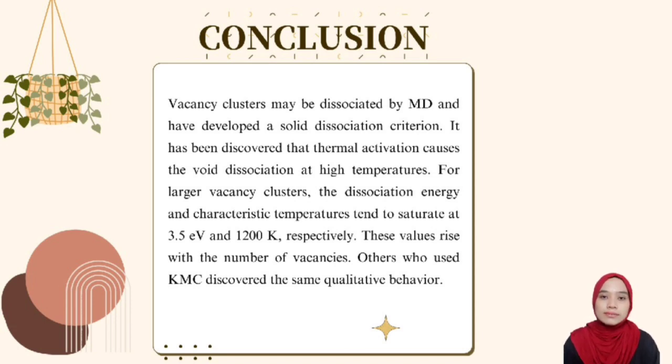As the single vacancy migration barrier is somewhat underestimated by the utilized EAM potential compared to the DFT value used by KMC, our estimates for dissociation energies and characteristic temperature are a bit lower. Therefore, in practice, we would anticipate a marginally higher stability for the voids.